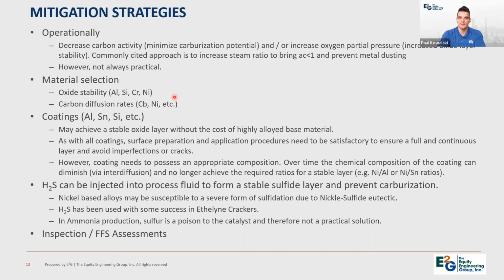Another item that needs to be considered with coatings, many of the coatings manufacturers and providers are aware of this, but based on, again, the environment and the chemical composition, the actual composition of the coating may change over time due to exposure to the high temperature environment. So, for example, there are several coatings that rely on an optimum nickel to aluminum ratio or nickel to tin ratio. And, following install, that ratio is ideal and will provide the required resistance to metal dusting. But over time, that ratio can actually change through a mechanism called interdiffusion.